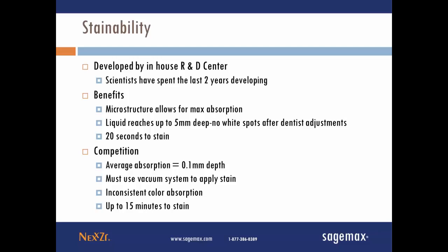A few more things that we see from our competition. We've talked about the ease of staining with our zirconia, having it only take 20 seconds for full absorption. Other systems require significantly more time, up to 15 minutes, and some of them even require the use of a vacuum system to apply the stain. Very good point. Also, the methods that we use here, we can just dry out stains in ambient air, and it takes only 5 minutes to dry.